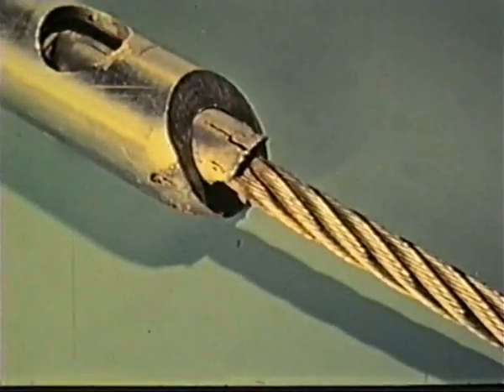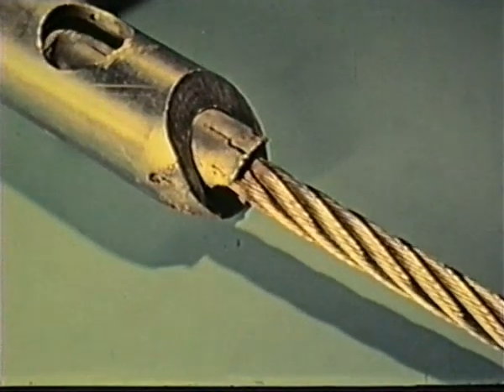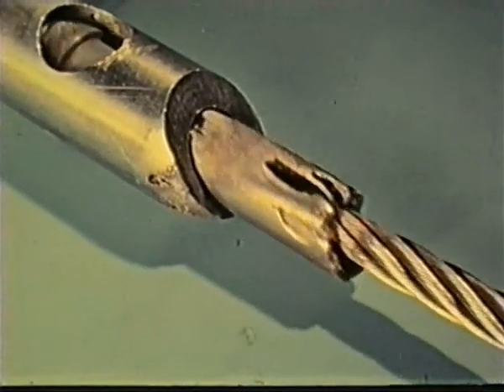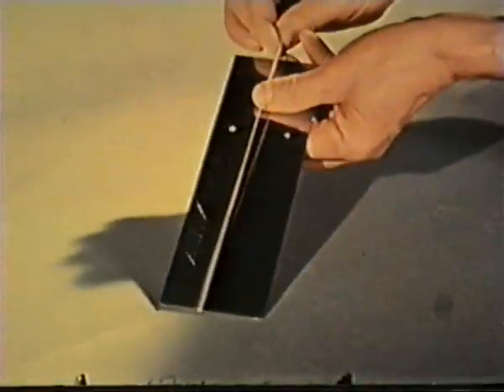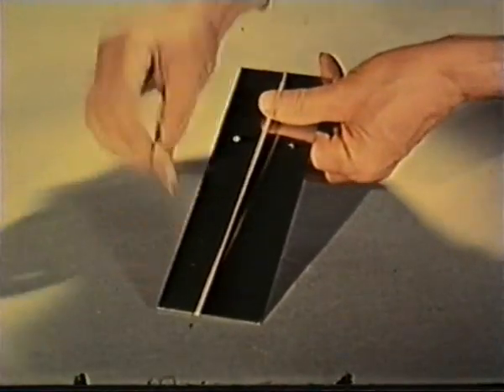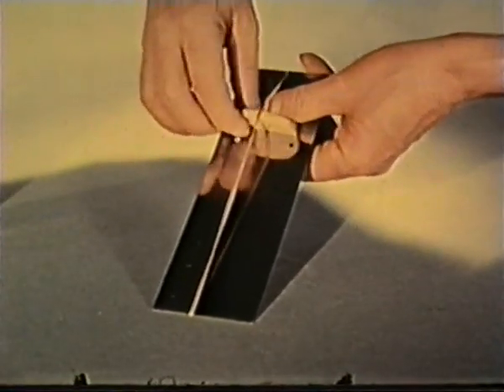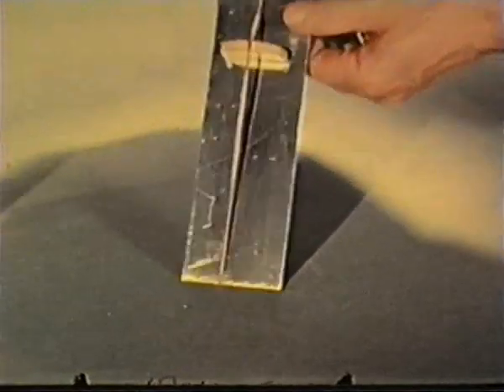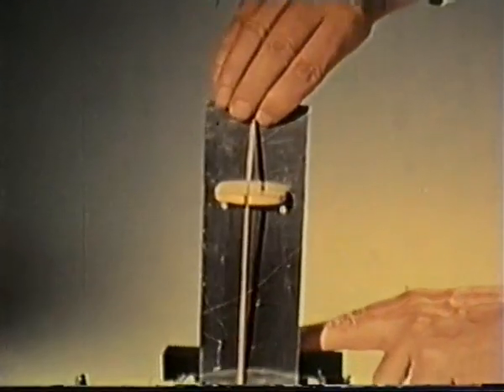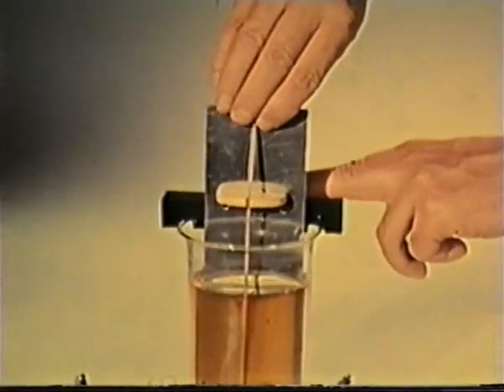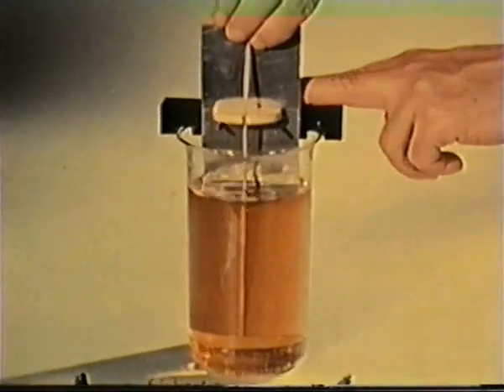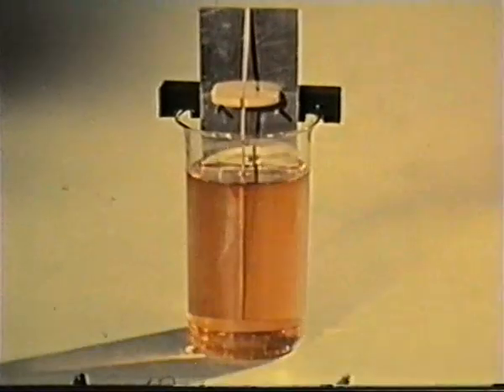The development of these so-called active-passive cells causes corrosion in crevices where passivity has been destroyed. We can demonstrate the damage that results from the breaking down of a protective film and the creation of active-passive cells. For example, let us observe the effect of a rubber band around a piece of stainless steel, which is immersed in a dilute solution of sodium chloride and ferric chloride.